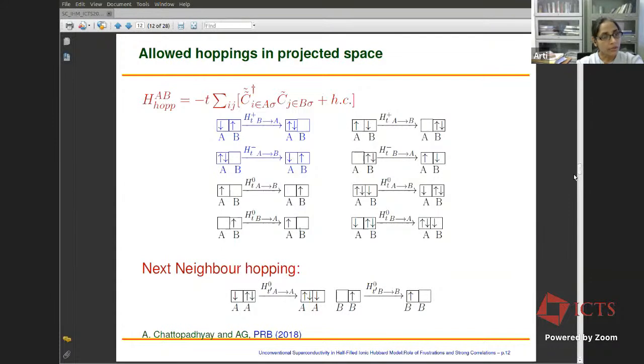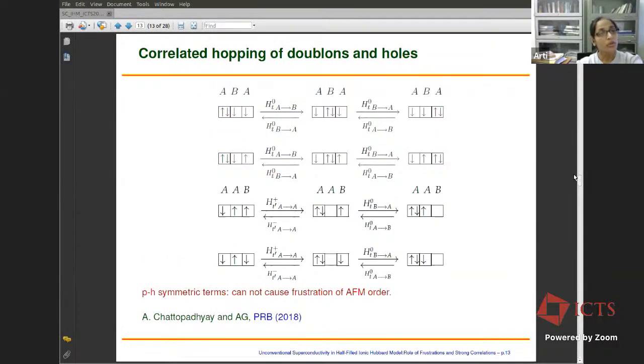Now there are some interesting correlated hopping of doublons and holes also taking place within A and B sublattice respectively through the higher order terms. So for example, there can be a hopping of doublon within A sublattice via spin flip or a spin preserved term on the B sublattice. And similarly, you can see a hopping of hole on the B sublattice via spin flip or a spin preserved term on the A sublattice.